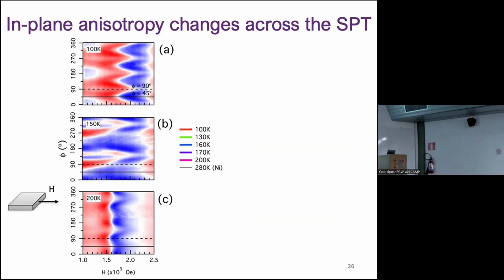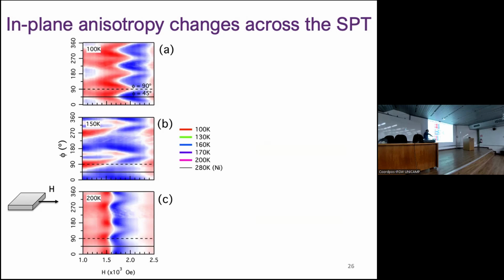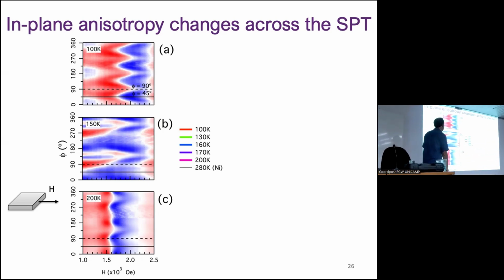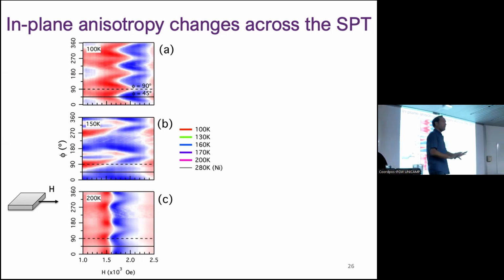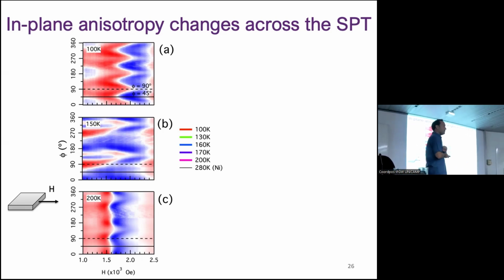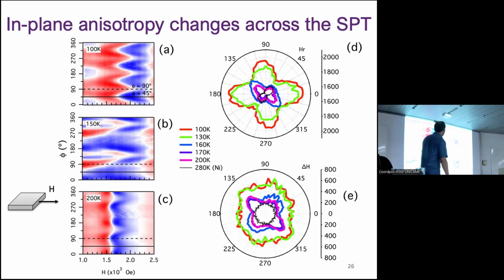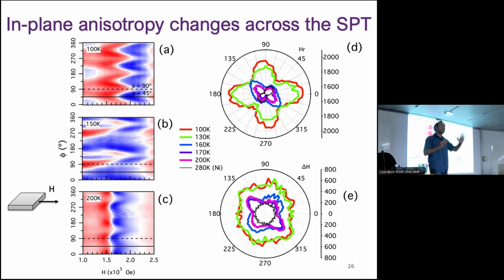And what you are looking at here is an angle that is the in-plane angle. So I'm rotating the sample this way, and if I rotate it 4 times, I get back to the same place. Okay, that's basically the symmetries of the material. This is connected to the symmetries of the crystal structure of the vanadium oxide phase. Okay, I plot here the resonance field, so the field at which the resonance occurred, and then how big the resonance, how big the transition is.